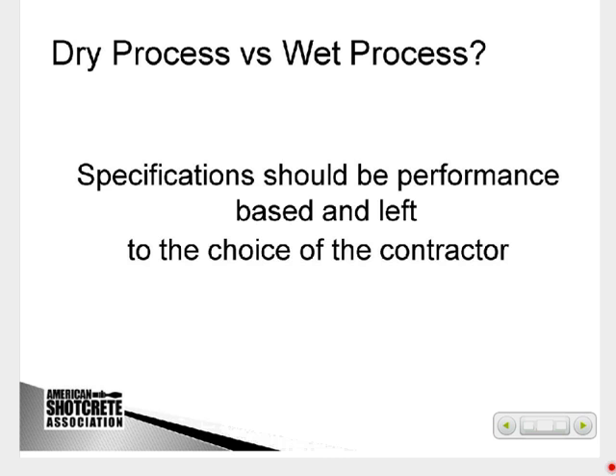If I was shooting a 2-foot thick shear wall, heavy reinforcing, I'd certainly be tending to use wet mix because you can get higher production. You probably get about 4 times the production in terms of cubic yards per hour with wet mix versus dry mix. So dry mix is good for smaller areas, good thin repair areas, where wet mix just generally would be better for thicker sections that would require a higher production rate.